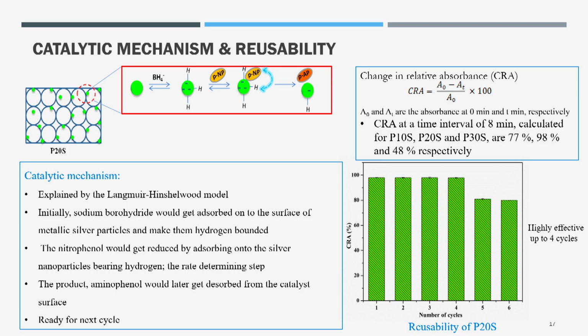I will show you the mechanism and you will be having better product formation. You can look into the next, this is the mechanism. So that is the PLA substrate. Initially sodium borohydride, the reducing agent, will anchor onto that. Then paranitrophenol will anchor on that. Since the structure is porous, as evident in morphology, it is more probable that a matrix is generated where sodium borohydride can come very close to the reactant, paranitrophenol, so that paranitrophenol gets reduced to paraminophenol.